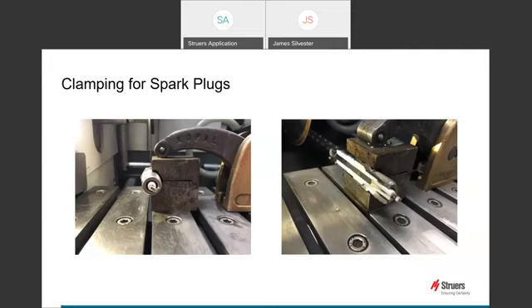The challenge we've had a few times is sectioning of spark plugs for quality checks. The dimensions of spark plugs do not allow typical clamps to hold onto the part securely enough, as the top and bottom of the spark plugs do not have the required cross-section to clamp onto, and also the electrode can be damaged if you clamp this way. A vertical clamp on its own doesn't give the required clamping force to keep the sample stable enough during a longitudinal cut, and so a custom holder is used, as shown in the slide, to assist spreading the clamping force and keep the plug where we need it to be for this cut. It also allows the clamping position to be much nearer the cutting axis, as shown on the left-hand image.